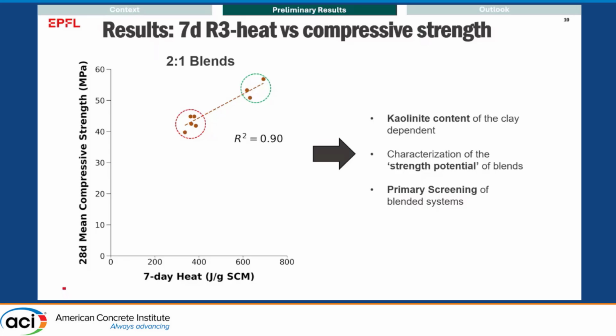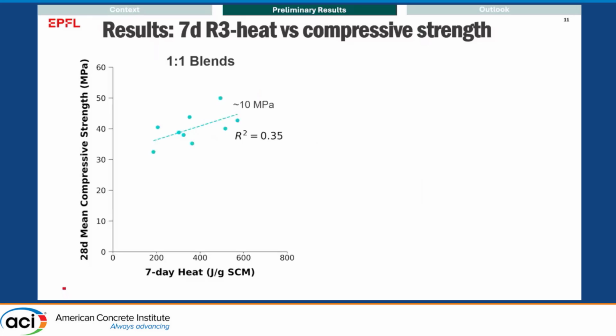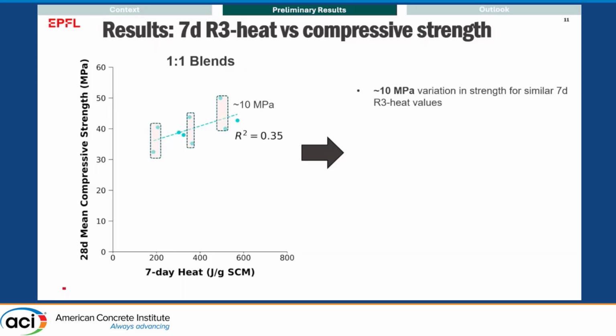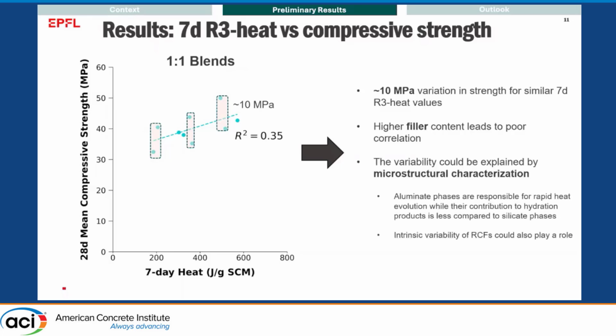But things get more interesting when you go into the 1:1 blends, because I don't know what to think of this data. All I can say is that for similar heat on the x-axis, you see a variability of almost 10 megapascals in the y-axis. So there is a variation of 10 megapascals of strength for similar heat values. This case is different from the previous case because here we are looking at 1:1 blends. And if you remember, 1:1 blends are the blends with higher filler content compared to the calcined clay, compared to 2:1 blends.